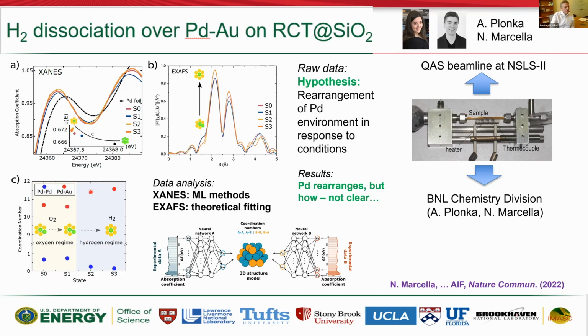So this is the meaning of this result. And in fact, you can even detect the change in palladium coordination number. When you have oxidation, palladium is segregated closer to the surface and has other palladium atoms nearby. That's why this coordination number is detectable. And then after hydrogen treatment, it dissolves and it's primarily surrounded by gold. So it is qualitative still, because we don't know what exactly happens, how many ensembles of which kind are there.